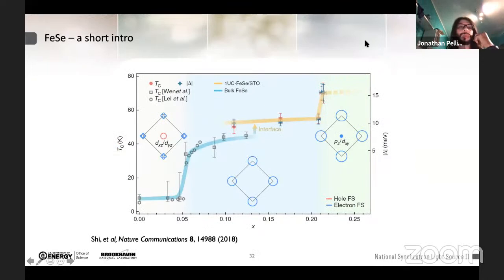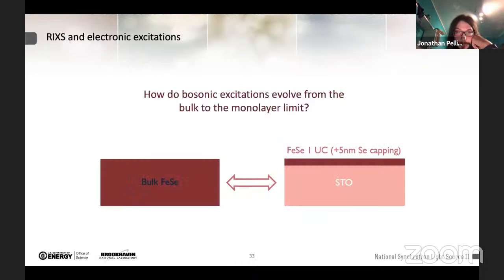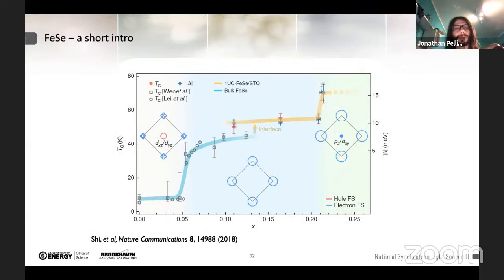But what is known is the evolution of the Fermi surface from the bulk case to the monolayer. In fact, if we look at the Fermi surface of the bulk, we have hole pockets at the zone center, at the gamma point, and we have electron pockets at the zone boundary. And if we look at the Fermi surface as measured by ARPES in the ultra-thin film, what we observe is that the hole pocket at the gamma point is gone, and we are in the presence only of electron pockets. So a Lifshitz transition takes place in between. And this is something that is important to keep in mind for what I will show you later on.